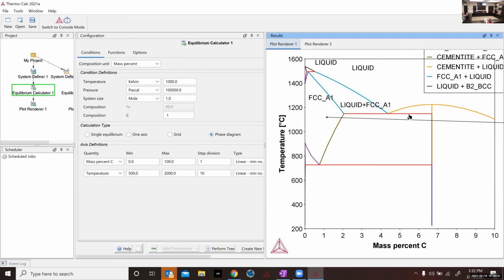But once you hit this red line right here, it is called the eutectic temperature. And below that, all of the liquid that's left that hasn't already transformed into cementite will transform into FCC plus cementite. So when you drop down below this red line, you end up with no more liquid. You end up with FCC plus cementite, 2 phases.